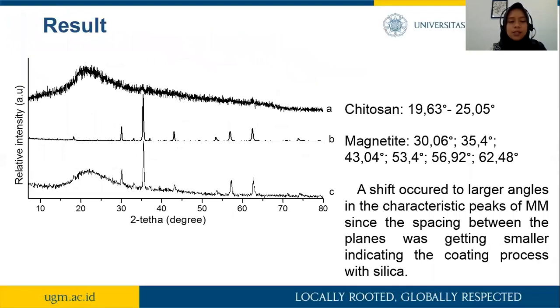And the second is our characterization with the XRD. The result is a shift occurred to large angle in the characteristic peaks of magnetite, since the spacing between the planes was getting smaller, indicating the coating process with silica succeeded. In the spectra at point C, we can still see the characteristic of magnetite. So the magnetite or chitosan is not damaged in the mixture.